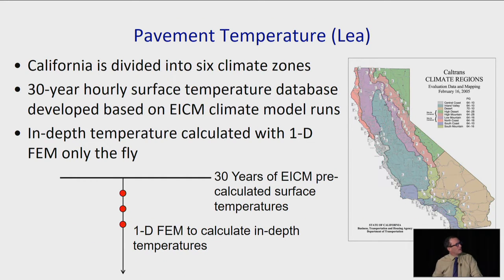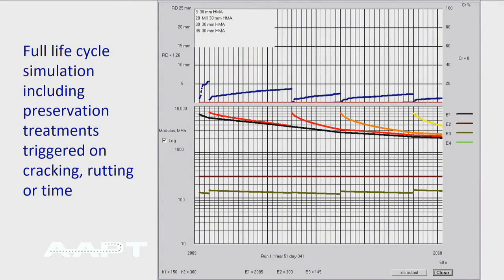For pavement temperature, we have a lot of climate zones. We're using EICM runs, but we're not running EICM. We use a 1D FEM that runs on the fly and gets the surface temperature out of our EICM database and then comes up with a temperature profile. And we've calibrated this and it works extremely well. And this is super fast, which allows us to run Monte Carlo. So what we can simulate, this is one example. We've also programmed into this that you can build in your pavement preservation triggers to trigger based on damage, cracking, or time-based maintenance and actually simulate the entire process over 40 years.